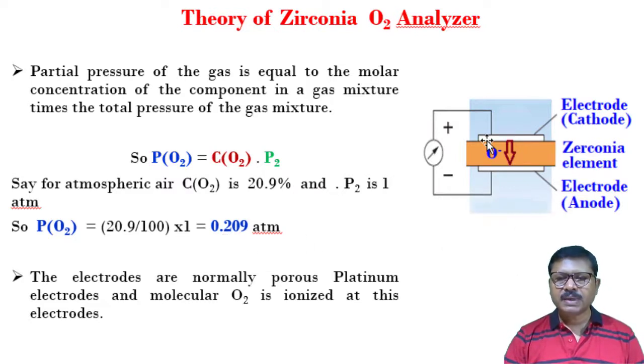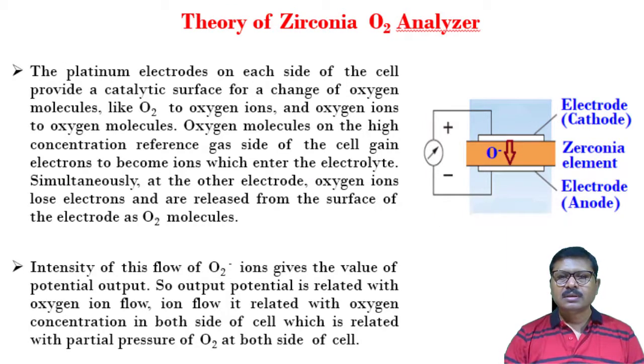The electrodes are normally porous platinum and molecular oxygen is ionized at this electrode. When the oxygen molecule or atom attaches to this electrode, at that point some chemical reaction will occur, and due to that chemical change the oxygen atom is converted to oxygen ions. The platinum electrodes on each side of the cell, this one platinum, this another platinum electrode, provide a catalytic surface for the change of oxygen molecules, and the change is from oxygen molecule to oxygen ion and then oxygen ions to oxygen molecule.